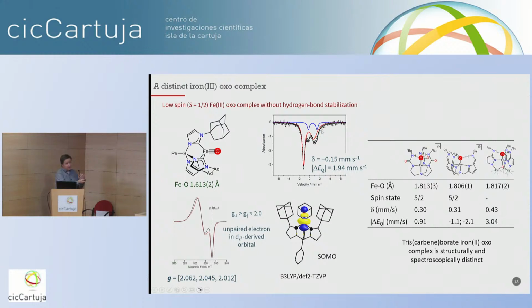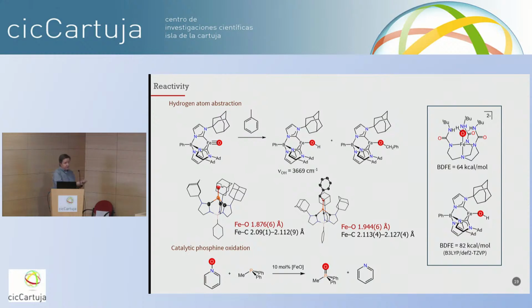Since this is iron 3, and it's a low-spin complex, so it has one unpaired electron, we can show that by EPR. So the EPR spectrum here is most consistent with the unpaired electron in a dz squared type of orbital, and that matches perfectly with the computed SOMO from DFT. So this dz squared type orbital. So this is a very different type of iron oxo from any other iron oxo, particularly iron 3 oxo that have been reported until then. But nonetheless, it's still reactive.